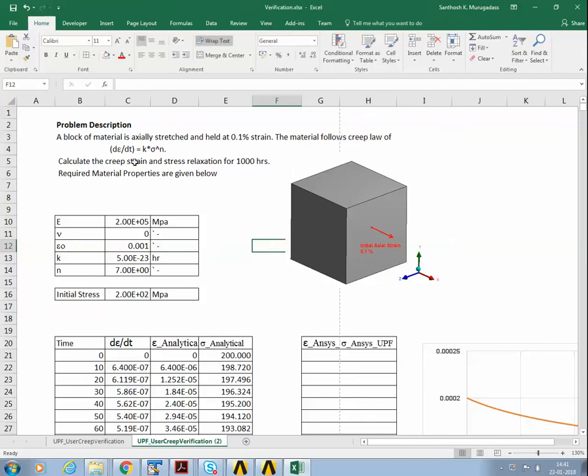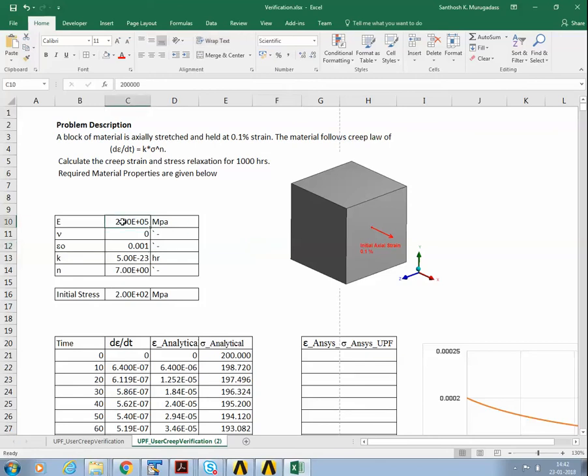This material follows a creep law as given here. The incremental creep strain is a power of the equivalent stress as given here. This is the creep law we need to use to predict creep strain and stress relaxation in this material. The material properties are given here: Young's modulus is 200×10³ MPa — typical steel — and the initial strain is 0.001. K and N are the material constants: K is 5.0×10⁻²³ per hour, and N is 7.